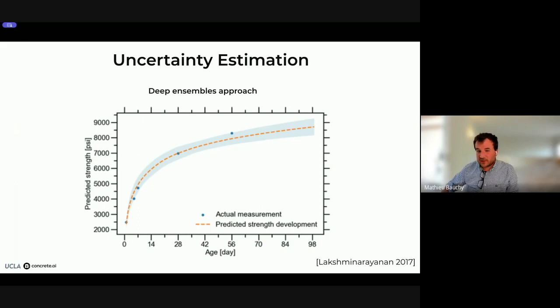And then the next thing is, again, we need to have a good way to estimate uncertainty. And uncertainty can come in many ways. It can be that maybe in our database we have several concretes that are close to each other but with different strength, and in that case we need our model to be aware of that. But there is also, whenever we extrapolate, we need to make sure that the more we extrapolate, the uncertainty of the model is going to increase, right? So for this we use an approach that is based on deep ensembles. So rather than training a single model, we train an ensemble of deep learning models, and basically we use that to estimate the uncertainty of every prediction that we make.